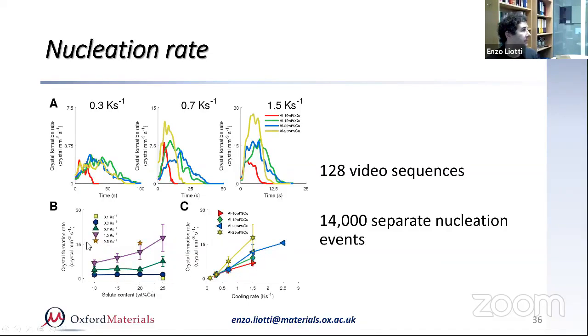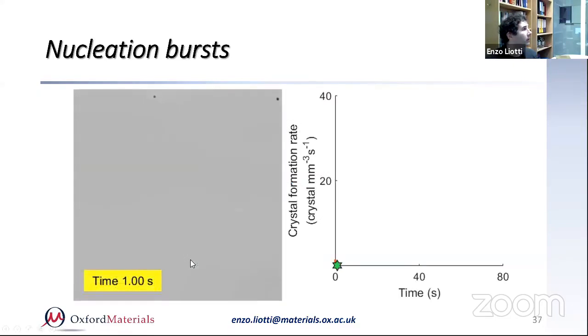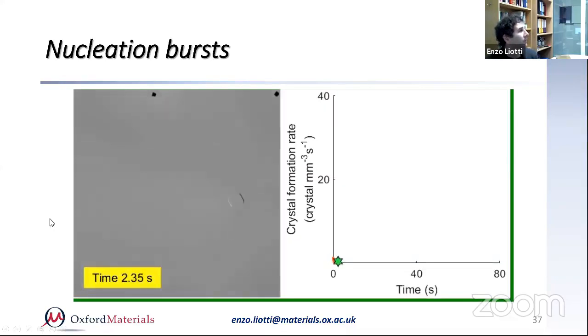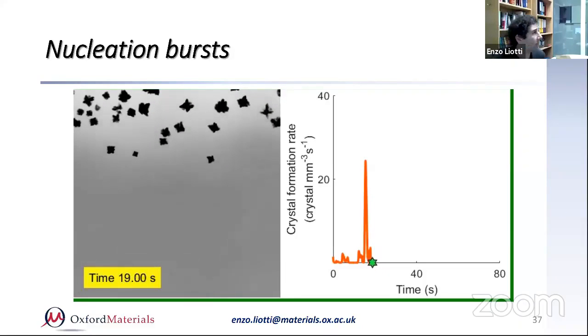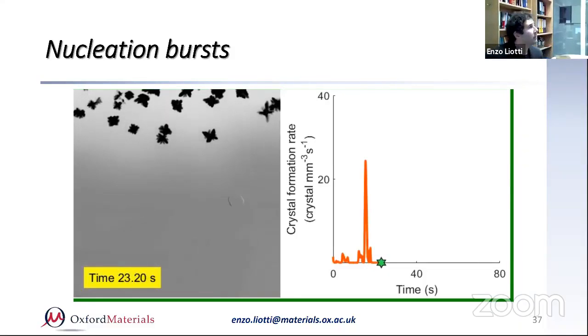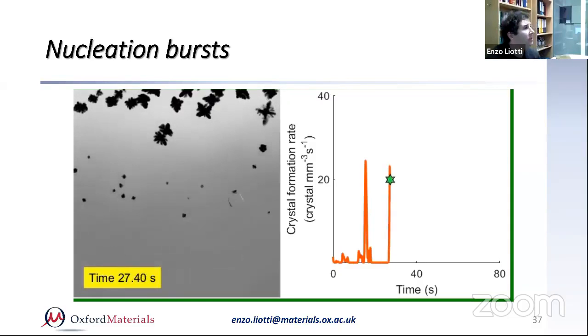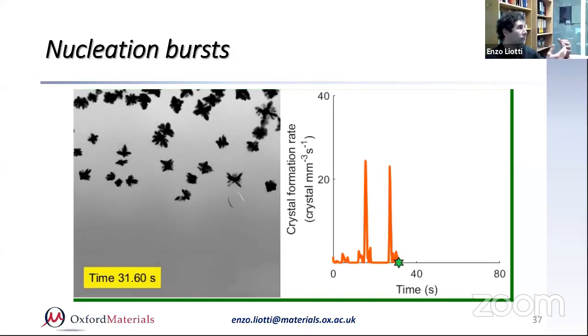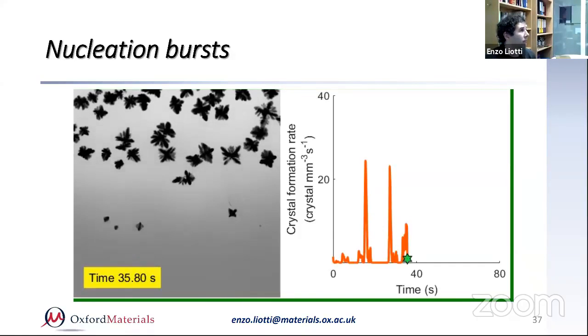And that's actually seen here as well in this figure in B, where you can see that the effect of the cooling rate was much more effective at high solute content compared to low solute content. Another interesting aspect that was found by analyzing all these data, and was always theorized, is that nucleation in a temperature gradient doesn't take place continuously, but actually comes in bursts. And as you can see here, this is a live graph of the formation rate of the crystal. And you can see within the video, there were essentially 3 big waves. So nucleation is not continuous, but it's almost recharging now, and then there will be a final wave that is taking place now.